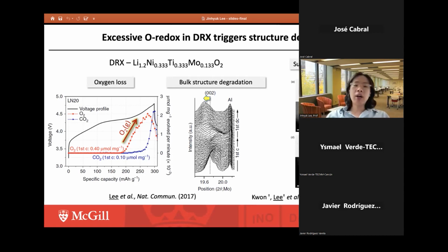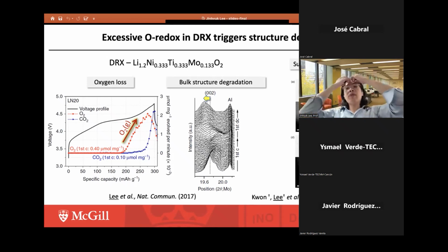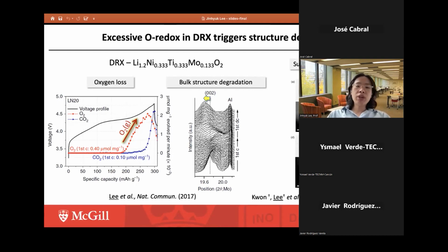And now if you look at this middle profile, these are the in situ XRD patterns of the lithium nickel titanium oxide during first charging and first discharging. Now we can see that the 002 peak has an irreversible shift, meaning that there's an irreversible cation rearrangement in the structure, resulting in bulk structure degradation. So obviously there is a critical failure of this material, and we also found that the surface can irreversibly change into a new structure, leading to poor performance of these materials. So overall, excessive oxygen redox in DRX has been shown to trigger structure degradation.